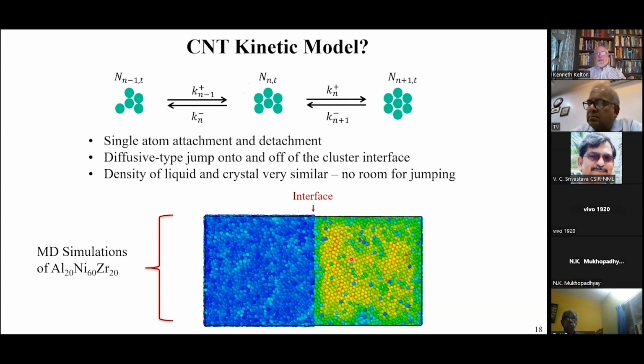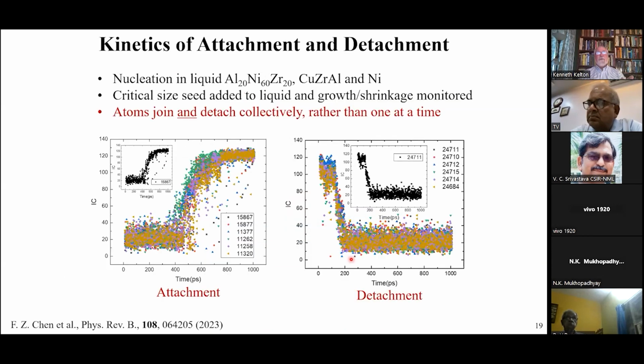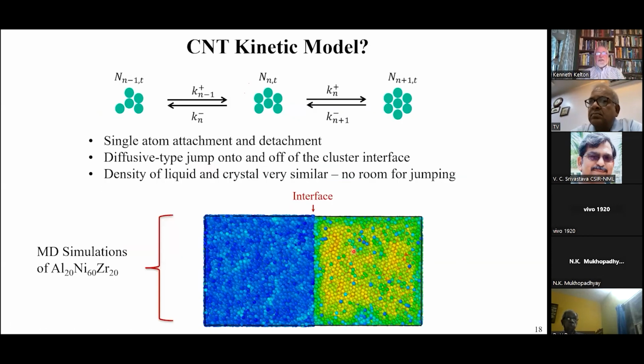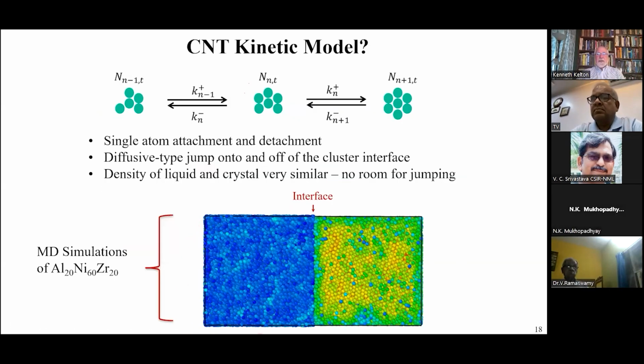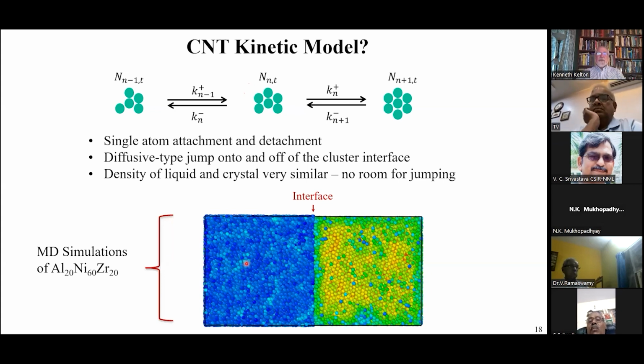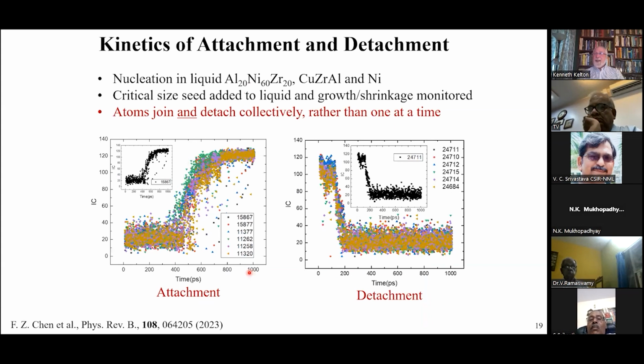Now, one of the ways we can investigate that is to put in seeds. Basically, you take a liquid like this, you carve out a piece of the liquid, and you put in a crystalline seed. And then you look to see whether that crystal seed grows or shrinks. And from that, you can determine the critical size. But you can also look at how the atoms are attaching. This is, again, nucleation I'm using to illustrate, but this has been observed in other metallic liquids as well, including monatomic nickel.